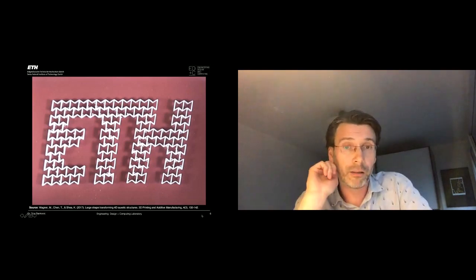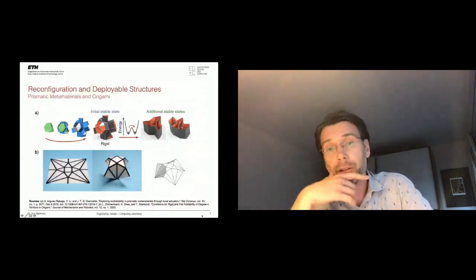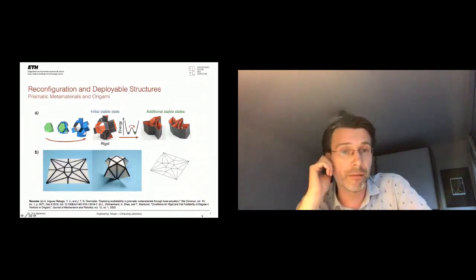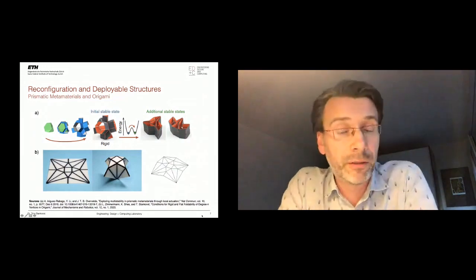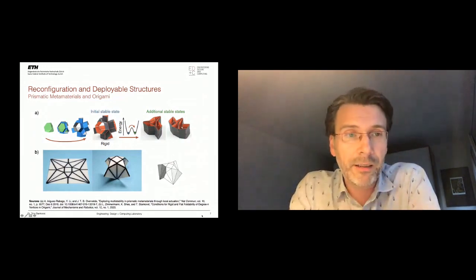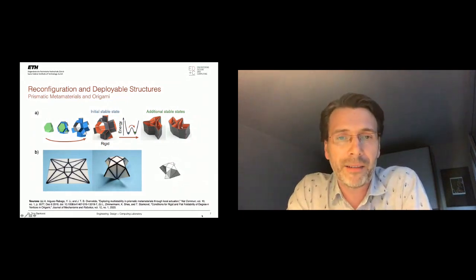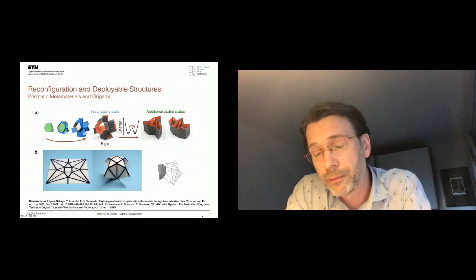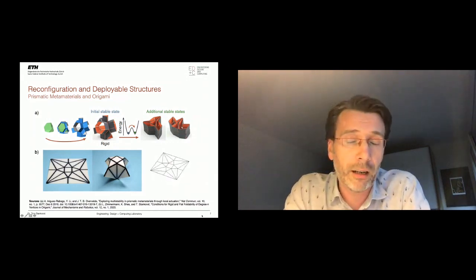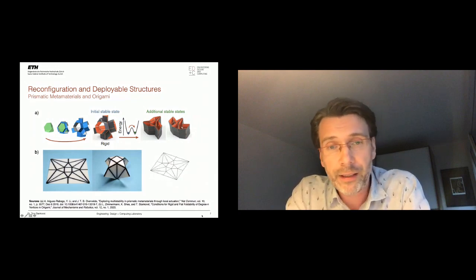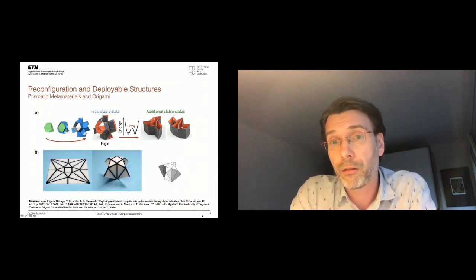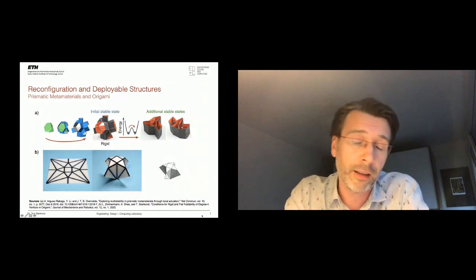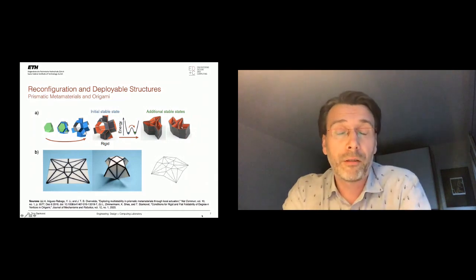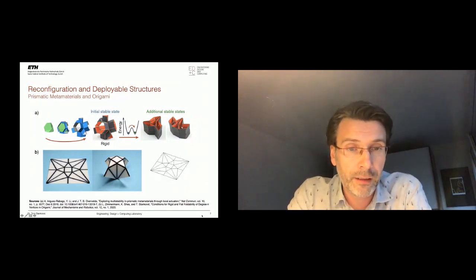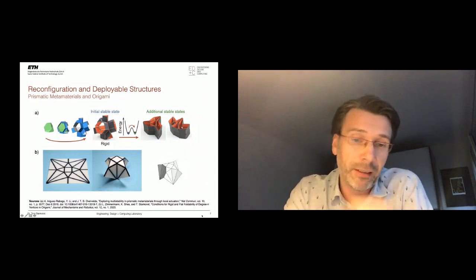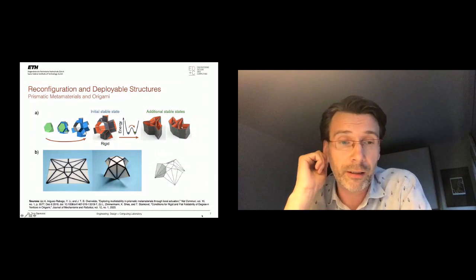Then, what Nick was also talking about, we have different deployable structures, of course, origami as well. And it's possible to design, in this case, in A, this is not actually origami, it's a prismatic structure with two different stable energy states that occur after snap-through buckling in the faces, and then we can create a configuration, and a different configuration gives different geometry, and then in the end gives different mechanical performance. And in B, I show an origami, which is another example that we did.